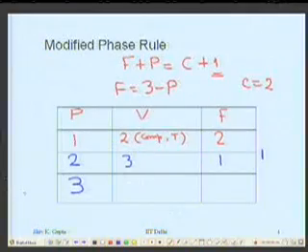Okay. Then if I have 3 phases present in the system, the variables I have are 4: composition of phases 1, 2 and 3, which are 3 variables, and temperature the 4th, and I have 0 degrees of freedom. So all the 4 will be fixed: composition of phases 1, 2, 3 and the temperature. Everything will be fixed. It is like a triple point in the unary system. We call such situations invariant. No variable can be varied. Okay.